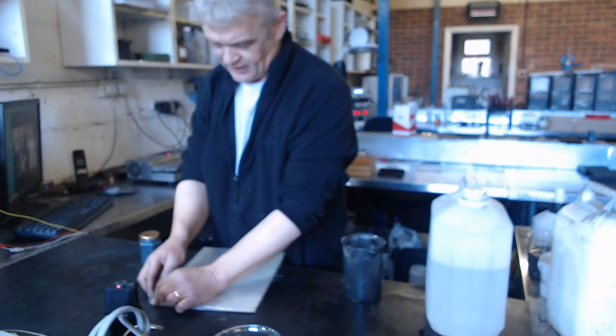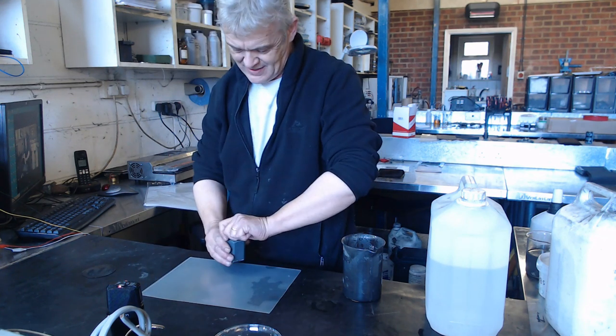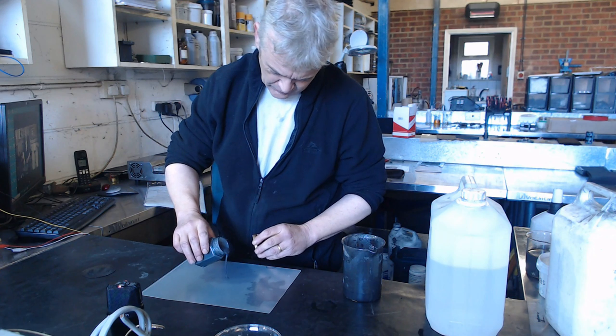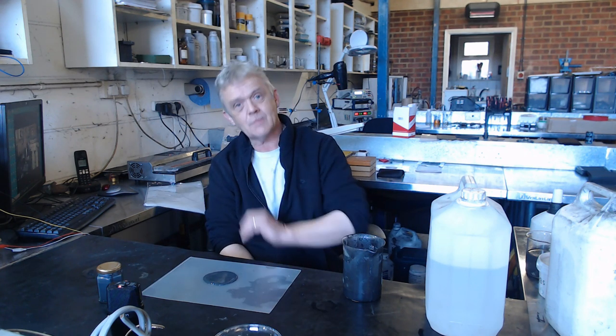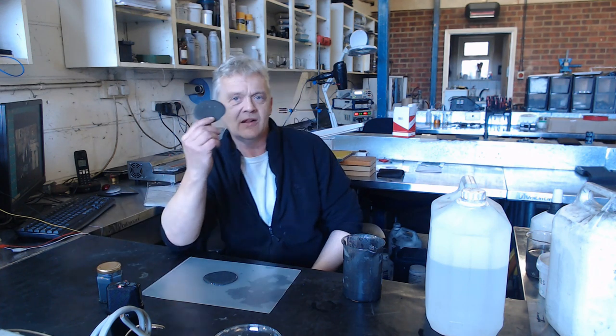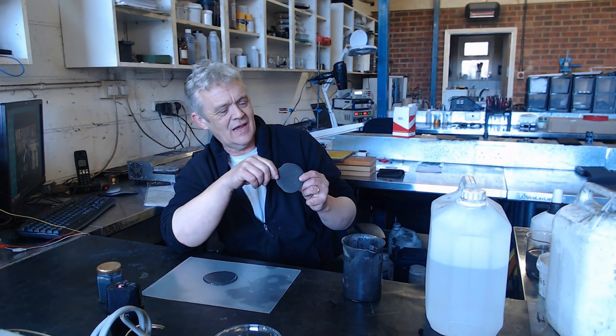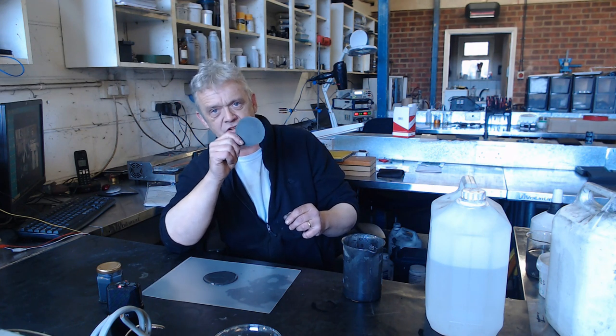Here's a little bit of high-density polyethylene used as a cover sheet. If I take a bit of HDPE and pour some of my acetone-graphene mixture on there, that's going to dry. By pouring it on there and letting it dry, all we're doing is losing the acetone. If you're doing it in bulk, you'd want to recapture that acetone using a hood and cooling. Once it's dry, that's what you get - a bit of graphene-filled ABS. You can chop it up, re-melt it, and turn it into a filament.